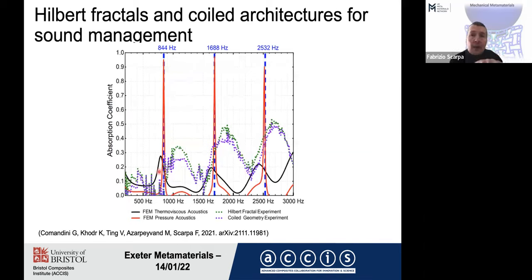Something that I also like to stress is that you can see here in this plot the resonance calculated simply considering the air cavities inside the fractals, and those calculated using the finite element simulated impedance tube. And the presence of viscosity in the air, especially inside the cavity, is quite important to get something that is comparable to the experiments. And actually, this is a fairly well-known fact if you want to simulate, for example, the acoustics of perforated panels. In perforated panels, you always need to consider in the simulation any kind of viscothermal effects.